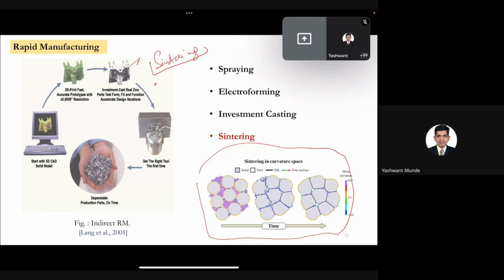So in sintering, you don't need melted liquid. You just have to go up to 60 to 80% of the melting point. You don't have to go very high. Like if you have to sinter a ceramic which has a melting point of 3000 degrees Celsius, you can easily sinter it at 1800 or around 1900 degrees Celsius. So that is the advantage of sintering. So we will see how we can use polymer 3D printed parts combined with sintering to make metal parts.